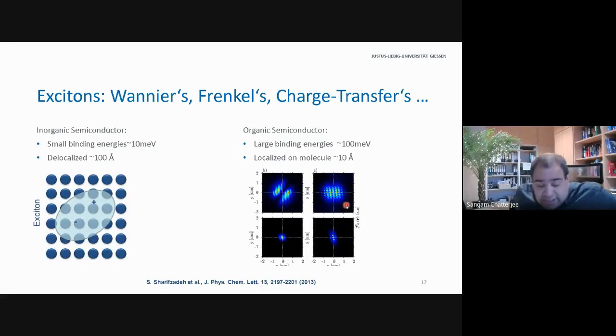Now, I talked a little bit about excitons already. What is an exciton? An exciton is something like a hydrogen atom on a dielectric background, if you want to call it like that. And typically, people tend to know excitons from inorganic semiconductors, at least in the places I was at, because you can basically discuss a lattice, you can go from real space where you discuss a lattice into momentum space where you have a band structure, and then you decide that the single particle picture of a band structure may not be sufficient, and you have to remember that you have electrons and holes or defect electrons, positive charges. These two are Coulomb charged entities, and they can actually bind.